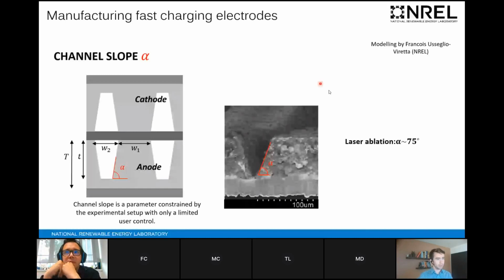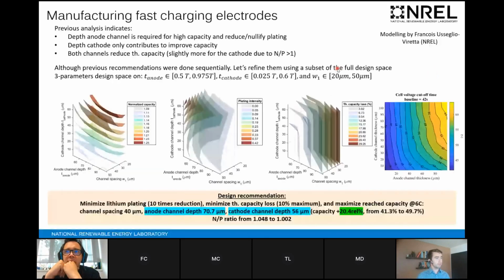This work was conducted by my colleague, Francois Usseglio-Viretta, at NREL. Francois conducted a very thorough parameter sweep based on those limitations. He looked at what is the optimal channel depth, with the systematic limitations that we mentioned, that can achieve high capacity during fast charging and a low plating intensity, with very little theoretical capacity loss. The capacity loss comes from having to remove some material to introduce these channels, so we want to minimize that. We set that limit at about 10% maximum loss of material.